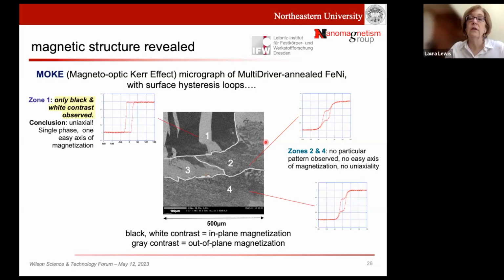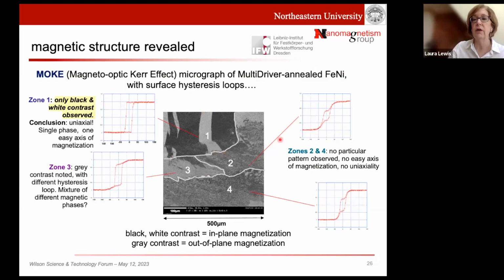Zone 1, immediately my colleague said, oh yeah, you've got a uniaxial material here. You have something unexpected. And these are little surface magnetic domains. I won't go into that. And then this one here, if you look at how this hysteresis loop looks kind of like a combination of this one and that one, this is probably a mixture. So we were very happy.